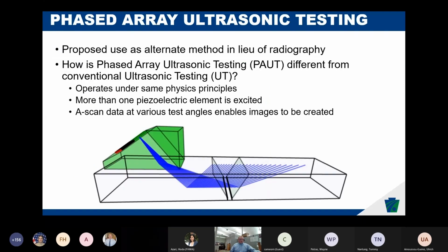So switching gears a little bit to phased array ultrasonic testing. Interestingly enough, the same fabricator that requested the use of digital radiography has now proposed using phased array ultrasonic testing in lieu of radiography. So phased array ultrasonic testing doesn't really differ that much from conventional ultrasonic testing. It still operates under the same physics principles. I mean, they really don't change.